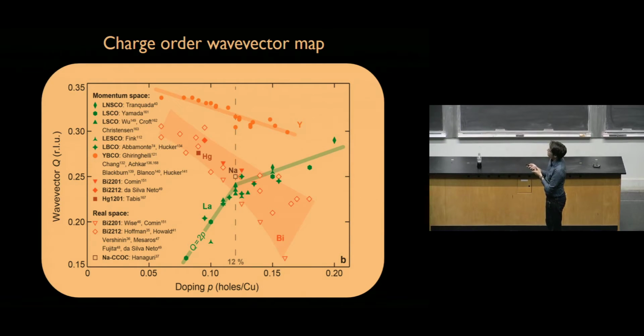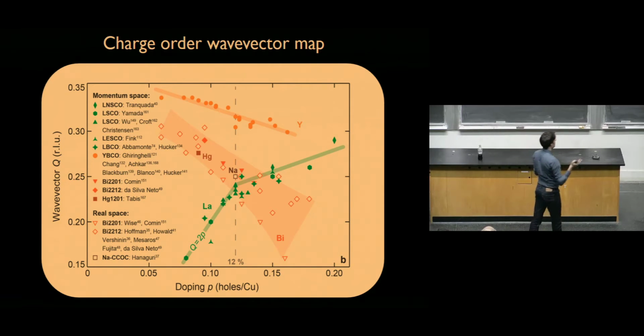And it changes in different ways for different compounds. And this is something that we don't yet understand. So it's there everywhere for all possible cuprates, again in the same range of dopings. But in some of them it has a given behavior as a function of doping, and in other ones it has an opposite behavior as a function of doping. So it seems like it's universal, but it also behaves a bit differently in different classes of compounds.